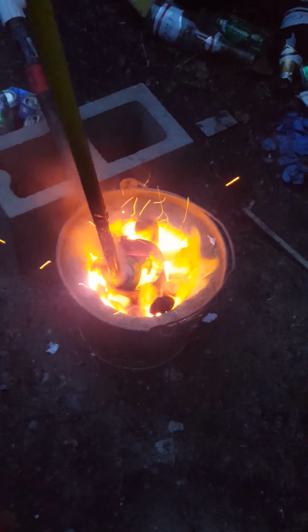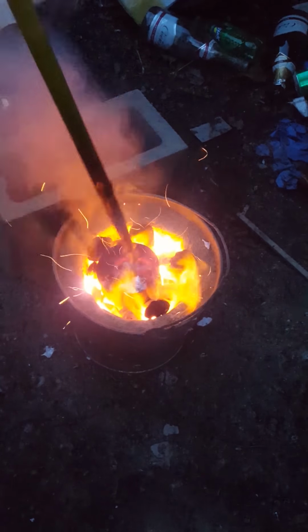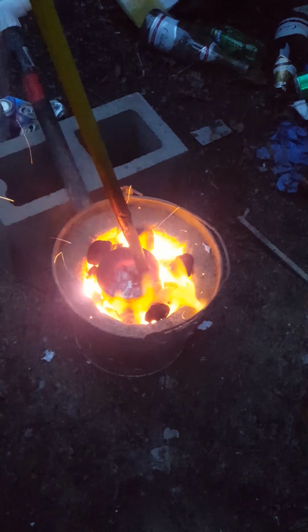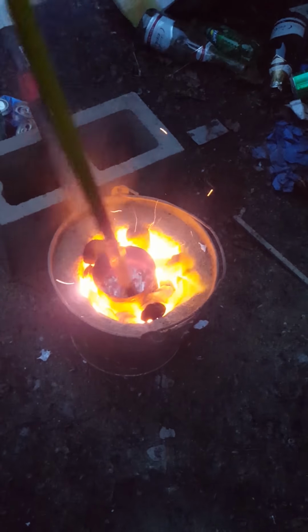After multiple uses of the foundry, fatigue and cracking appeared on our foundry elements. The multiple pours that we did allowed us to improve on our processing technique. This, however, created an issue that the temperature of the molten aluminum exceeded the melting point of the muffin tin, which caused a breach in the mold. We then used a steel paint can that was able to handle the energy for our later ingots.